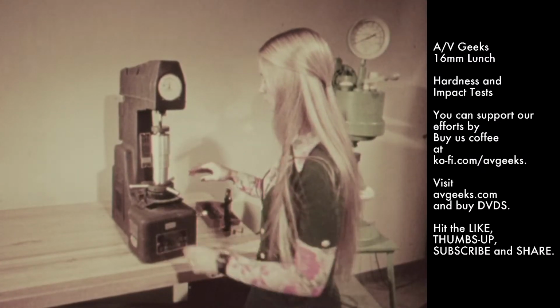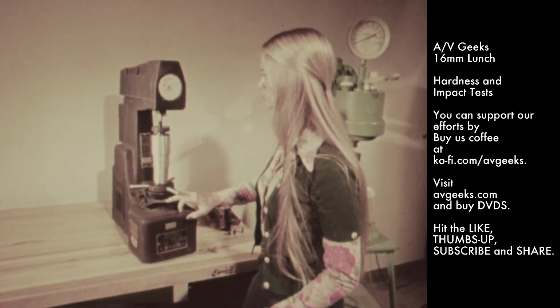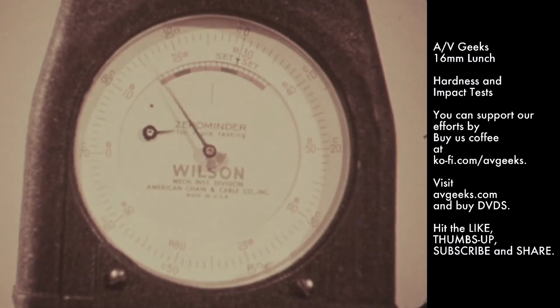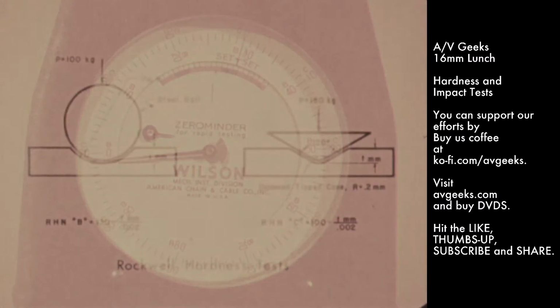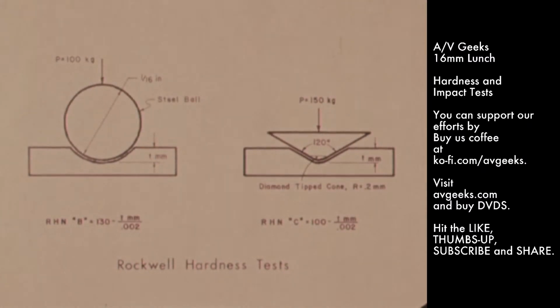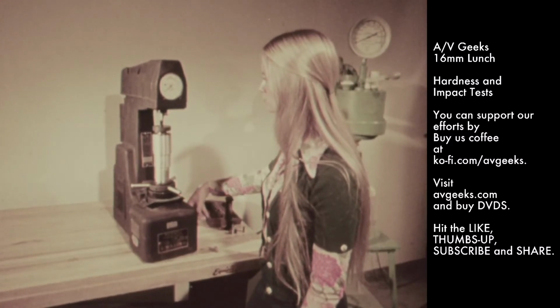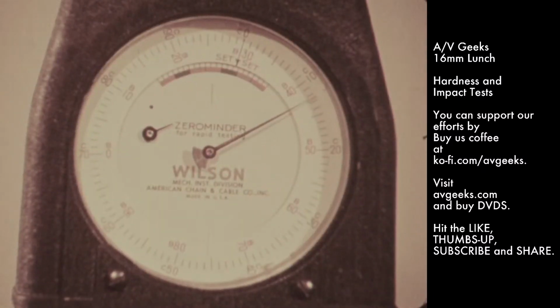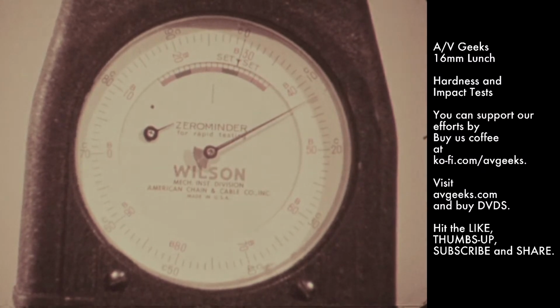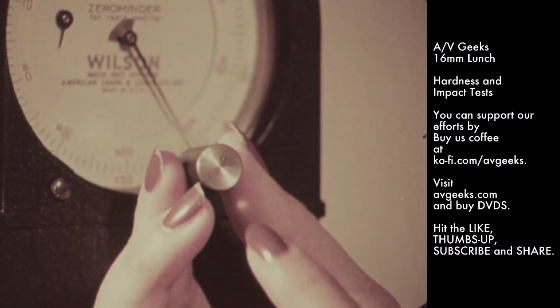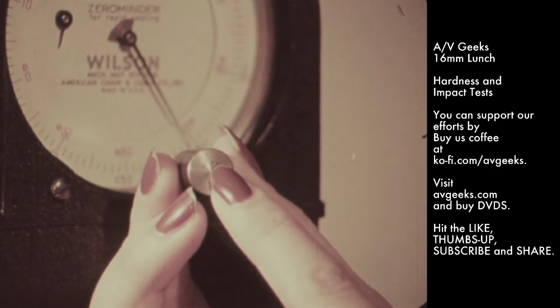The major load of 150 kilograms is applied when the load lever is tripped. The dial gauge is marked to subtract the depth of penetration from an arbitrary value so that a softer material yields a lower reading than a harder one. When the load is removed, the dial gives the reading directly. In this case, C13. The specimen has been indented by the cone. The indentation is quite small.